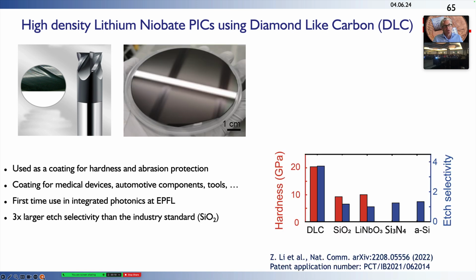carbon, which is a material actually that is used as a protective coating for medical devices or razor blades. This material has a hardness of diamond, but it can be deposited very simply by decomposition of methane gas in the reactor. And it serves actually as a superior photomask for materials that are hard to etch, like lithium niobate, lithium tantalate.